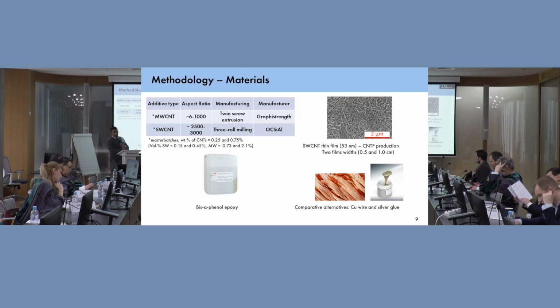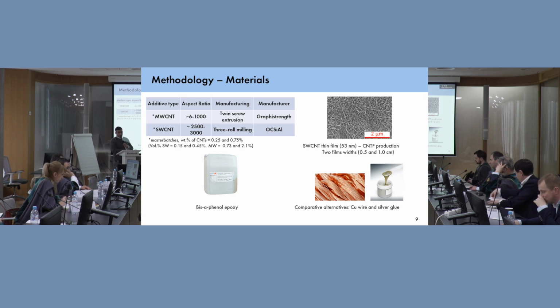So, of course, we wanted to use CNTs in this experimentation and dissertation. We use multi-wall carbon nanotubes and single-wall carbon nanotubes. For multi-wall, the aspect ratio is between 6 and 1,000, according to whatever dispersion we have from the manufacturer. For single-wall carbon nanotubes, it is generally between 2 to 3,000, and the manufacturing method here is because we used master batches. We can go into this later as to why, but basically they are pre-dispersions which allow easier integration into further composite manufacturing. Now with single wall, for our carbon nanotube fiber production, we use single wall carbon nanotube thin films produced by our laboratory using the wet pulling technique.